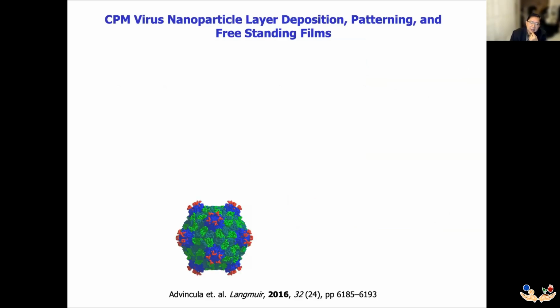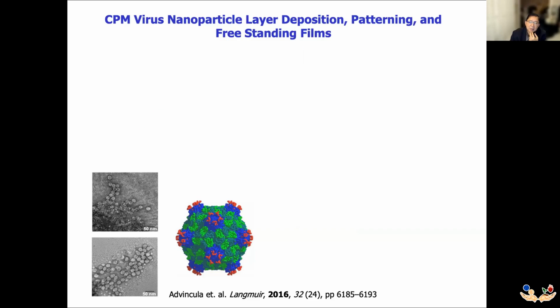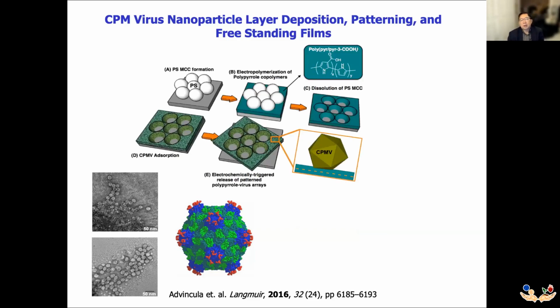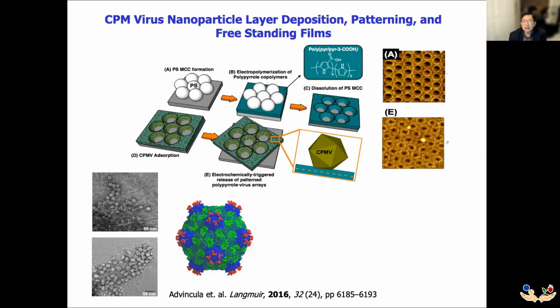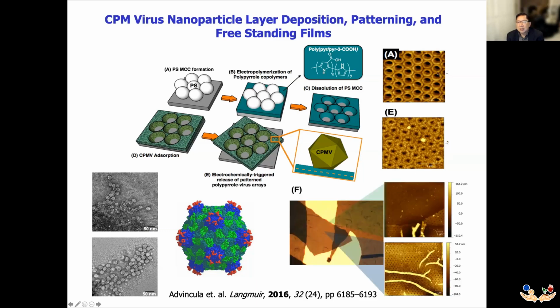Finally, I can demonstrate that these cowpea mosaic virus nanoparticles are capable of forming films. So in this case, if we go back to the full templating with colloidal particles and then grow polypyrrole around it, remove the original template, and then finally introduce the viruses, the question is will they go and will they end up forming layers? And the answer is yes. You can see the viruses here basically surrounding the holes of the arrays, indicating that the viruses would like to settle on the surface as well. And we can even liberate these patterns as films or freestanding films, showing that it's possible to have a very high concentration of the viruses in a templating manner or procedure.